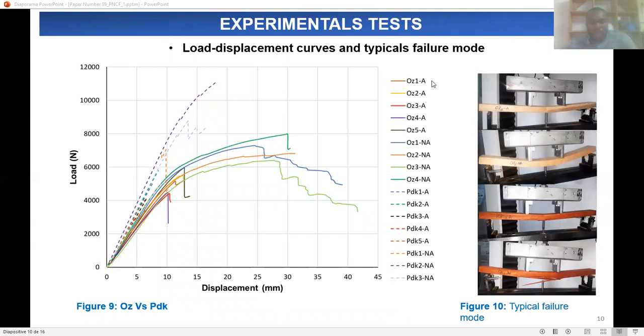So here we have the load displacement curve in Figure 9 and the typical failure mode observed during the test, Ozigo versus Padouk specimen. According to the load displacement curve, it is noted that the stiffness and maximum load of the lamella without finger joint are higher than those with finger joint. On the other hand, for the majority of Padouk specimens, the first crack appears in the elastic domain, while for Ozigo specimens, it appears in the plastic domain. This reflects that Padouk and Ozigo have a quasi-fragile and ductile behavior at failure respectively.